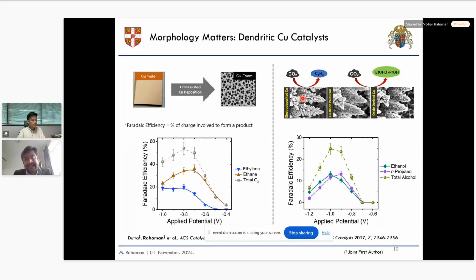For example, the as-prepared copper dendrite forms quite selective ethylene, around 35%. And then if we activate the catalyst and make some nanostructure on the surface, we can get ethanol and 1-propanol at around 25% Faraday efficiency on this activated oxide-derived copper material. So we can see that the morphology as well as the activation approach is very important to change the selectivity of the carbon dioxide conversion process from one product to another.